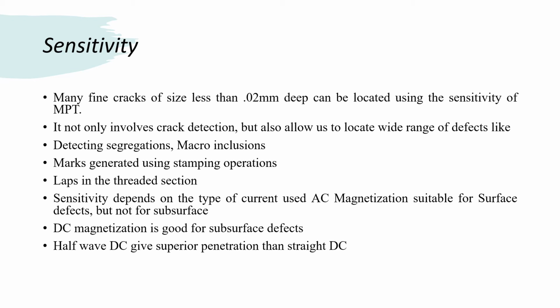Many incipient fatigue cracks and fine grinding cracks having sizes less than 0.02 mm deep and a surface opening of 1/10 of that.